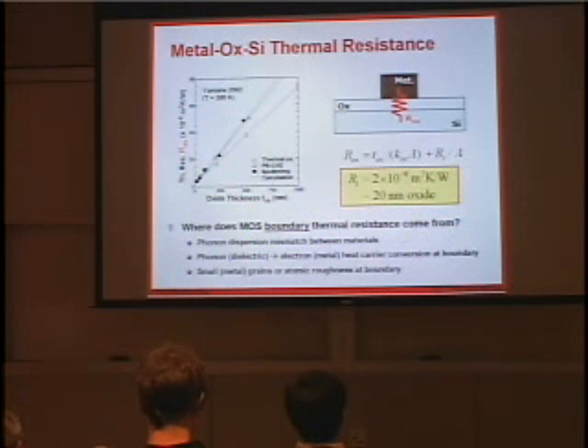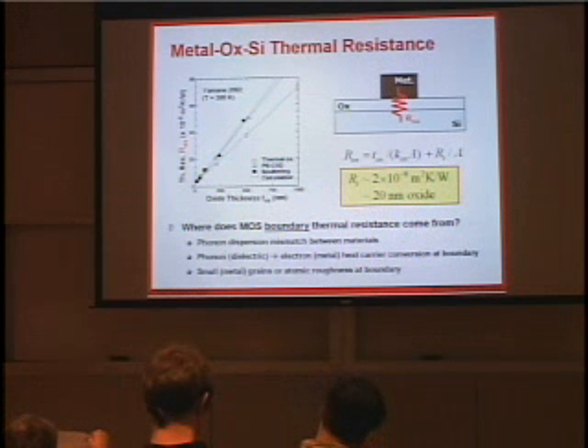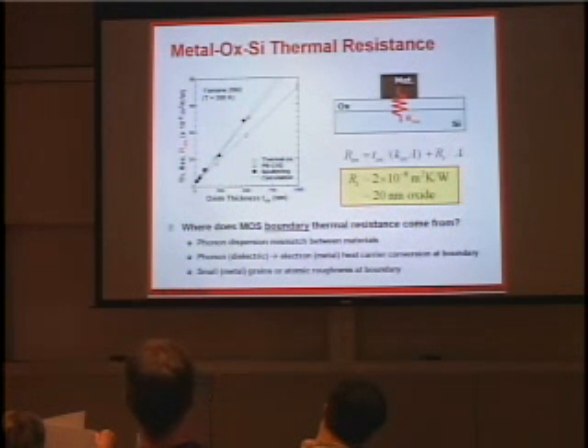There's still some debate in the literature about where this boundary thermal resistance comes from. It can come from phonon dispersion mismatch between materials. It can come from the fact that the phonons are the heat conductors in dielectrics, while the electrons are the heat conductors in the metal, so there's heat conversion at the boundary. And it can also come from small metal grains or atomic roughness at the boundary. So perhaps improving processing conditions might improve this, although this is the number that I've used in my simulation.